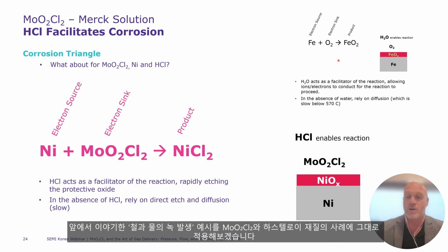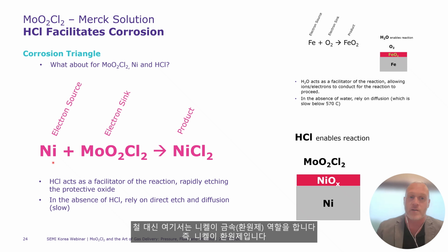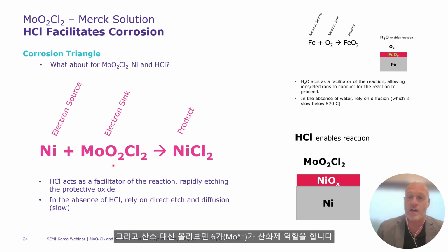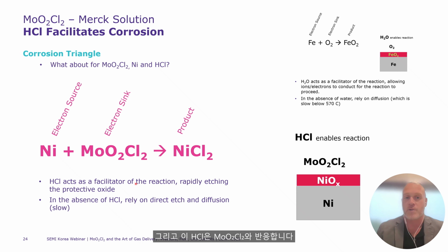So if you think about the rust and water example, let's take that to moly dichloride and Hastelloy base as an example. So instead of iron, we have a nickel source. That's the reducing agent. Instead of oxygen, we have a molybdenum 6 oxidation state. And so does this reaction proceed in the absence of a facilitator? So in this case, that facilitator is very likely going to be HCl. Any moisture around at these elevated temperatures is going to be in the HCl state. It'll react with moly dichloride.